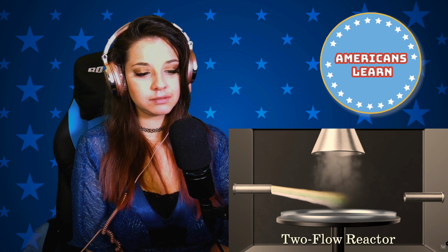The gallium nitride reactant gases had been rising in the hot chamber, mixing in the air to form a powdery waste. But the second nozzle released a downward stream of inert gas, pinning the first flow to the substrate to form a uniform crystal. For years, scientists had avoided adding a second stream to MOCVD because they thought it would only introduce more turbulence. But Nakamura used a special nozzle so that even when the streams combined, they remained laminar. He called his invention the two-flow reactor.